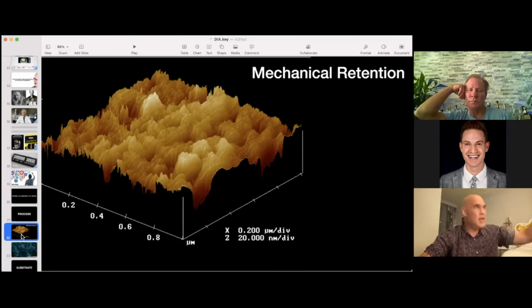Michael Buonocore showed that, and it still works. That's how you achieve mechanical retention on enamel. Now, when you go to zirconia, it's a different story because you can't etch zirconia. You cannot. You need to sandblast it in order to achieve mechanical retention. So you're changing your method based upon your substrate, okay?